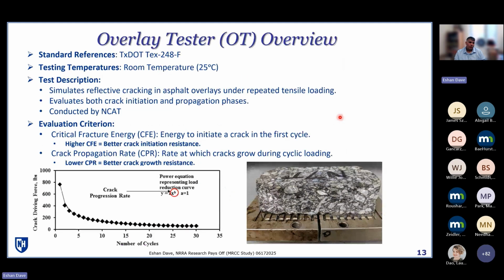Overlay tester. So the Texas overlay tester, again, was developed and used by Texas DOT through efforts of the Texas A&M Transportation Institute. Also another test at room temperature conditions. And the idea here is somewhat of a simulative test procedure where you have your test specimen glued to metal plates with a joint in them, and then those plates open and close in order to form the crack as it travels through this specimen.